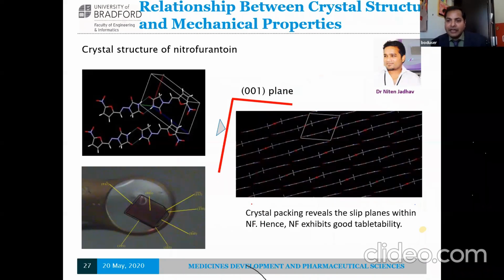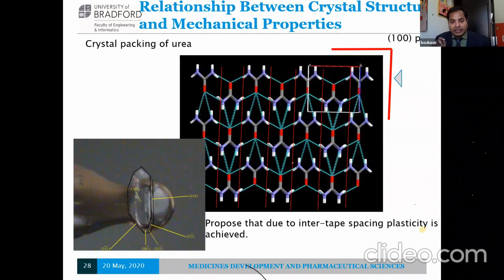At Bradford, Nitin has prepared these materials and studied these systems. If you look at the crystal structure, nitrofurantoin itself is forming some layered structure. So between these layers, you have weak interactions that could resist any force that is impacted on the system. As such, nitrofurantoin offered some slip planes and also some resistance compared to the co-crystal, in fact.